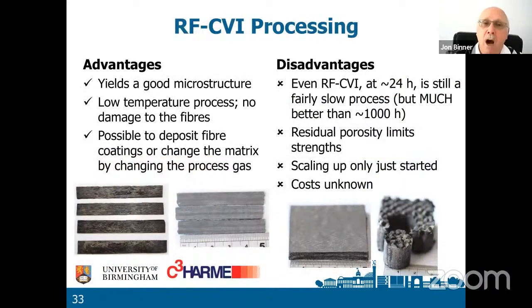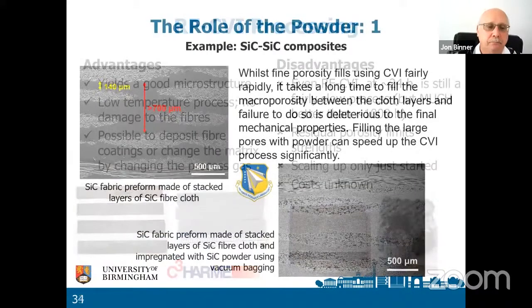So the RF CVI process has a number of advantages. It yields a good microstructure. It's a low temperature process. There's no damage to the fibers. It's possible to deposit fiber coatings or change the matrix by changing the process gas. But it has some disadvantages. At 24 hours, it's still a fairly slow process. Residual porosity does limit the strength. With CVI, you won't get much more than 90% dense. Scaling up has only just started, and of course, costs are unknown.